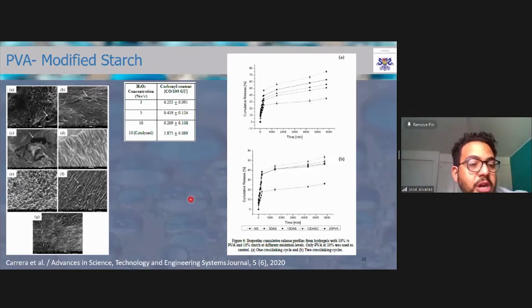So we said, what happened if we partially incorporate oxidized starch into the PVA hydrogels? Can we go down on the PVA concentration and still have stable hydrogels? We were able to go down to 10% PVA, in some cases 5% PVA, and form stable hydrogels.